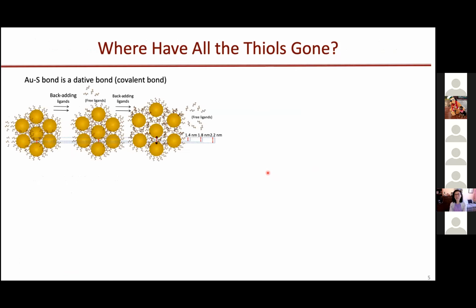So what have the thiols done to the gold nanoparticles to induce different elastic responses in the films? One theory is that because the gold-thiol bond is covalent and strong, thiols will always stay on the gold once bonded. In this picture, the gold nanoparticle is always fully ligated, and the free thiols are just space fillers.